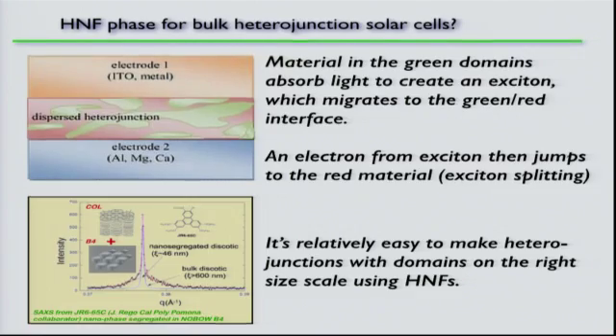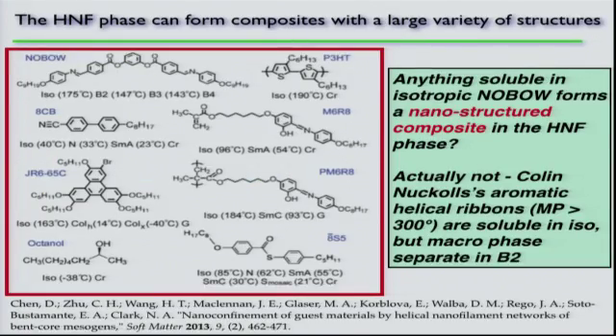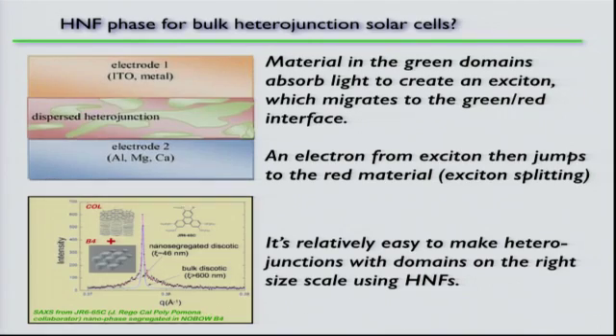Actually, Colin Nuckolls has this aromatic helical ribbons thing that melts at above 300 degrees. So you put that in, it's soluble in the isotropic of NOBOW, but you cool it down, and when you go into the B2 phase, Colin's stuff crystallizes out. So we weren't able to get those ribbons into the helical nanofilaments, but that's something we're going to do. I'm sure it would work if we had an isotropic to B4 material.